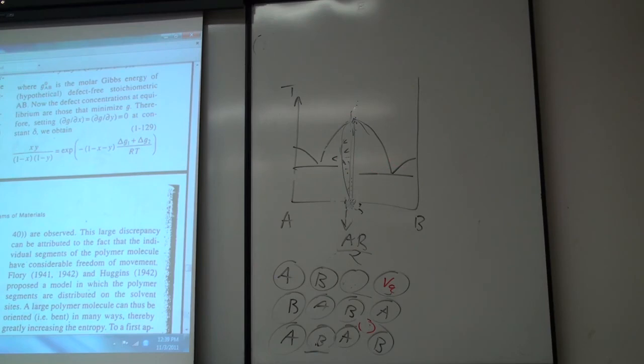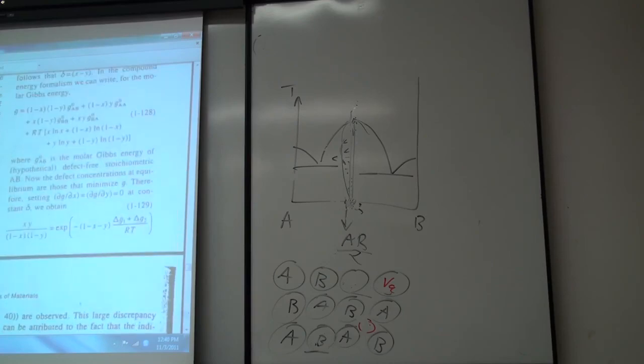This also generally gives you a fairly good approximation. If you can measure the concentration of vacancies, then the concentration of vacancies times the concentration of the other majority defect will always be constant. Which is useful when you're talking about looking at transport properties. I'll talk about that a bit later. Okay, that's a good place to stop.